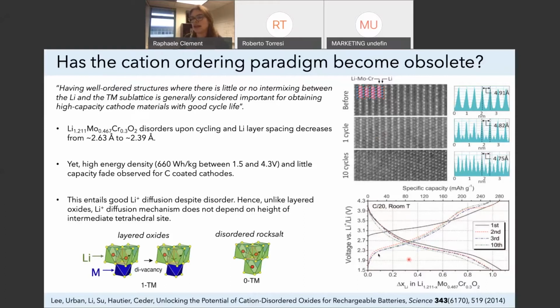So we're not relying anymore on what we call one transition metal channels. And the reason why we call them this way is that for lithium to hop between an octahedral site to an adjacent octahedral site in the lithium layers in your layered compounds, it has to go through a tetrahedral site here. And in this case, this tetrahedral site has 4 faces sharing 4 octahedra.